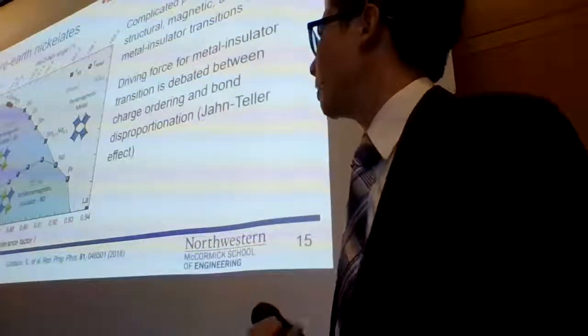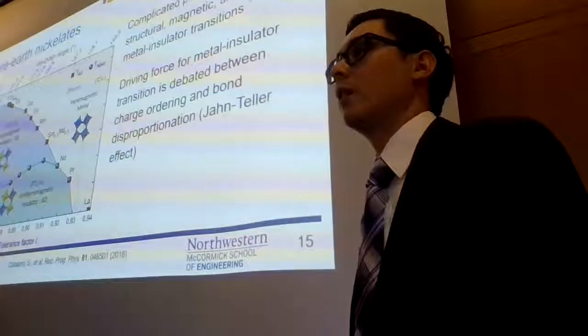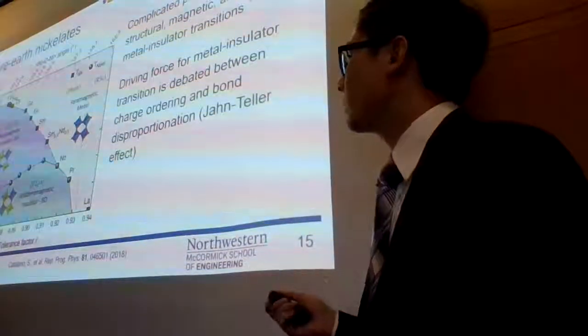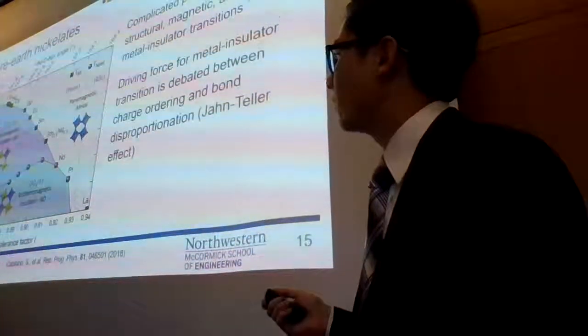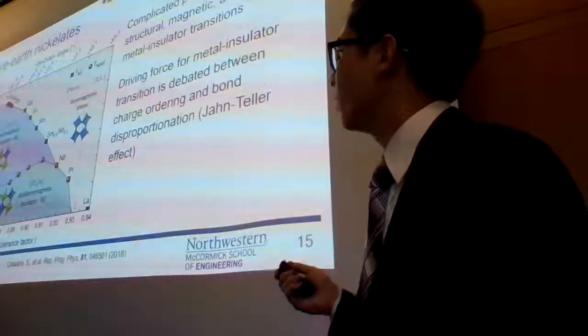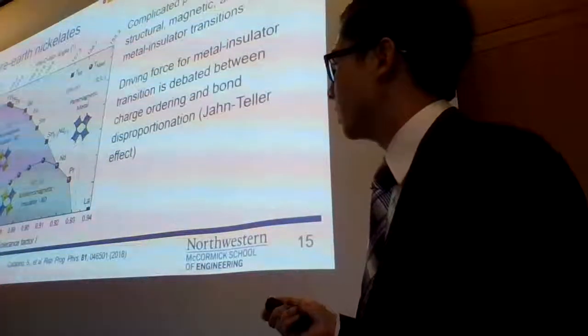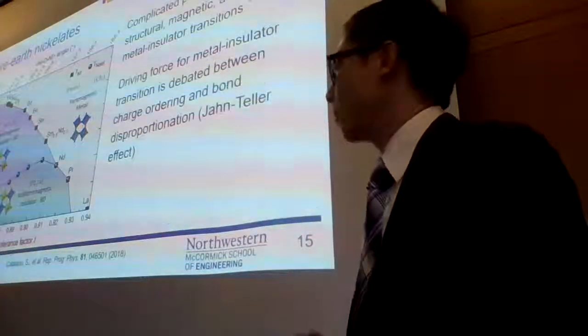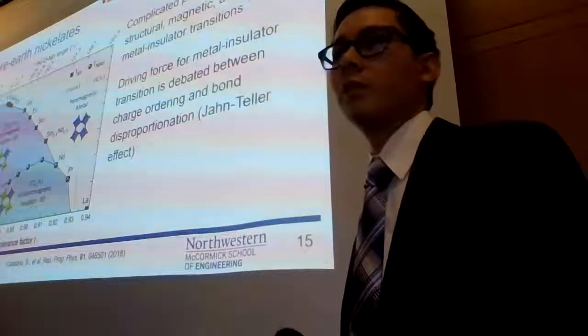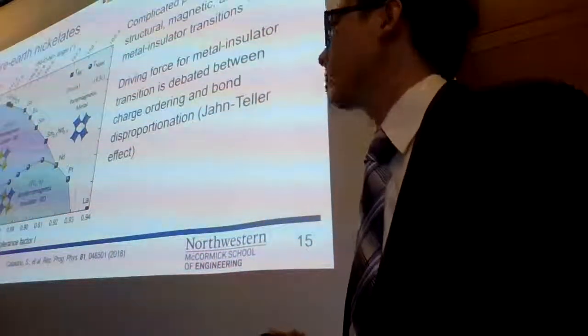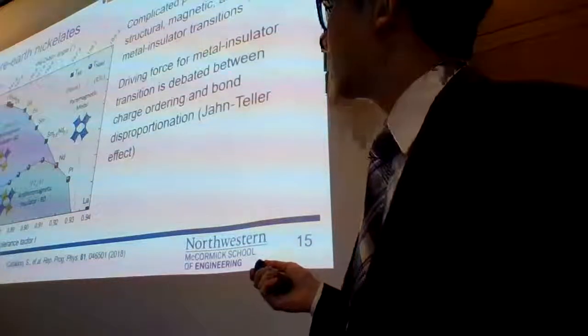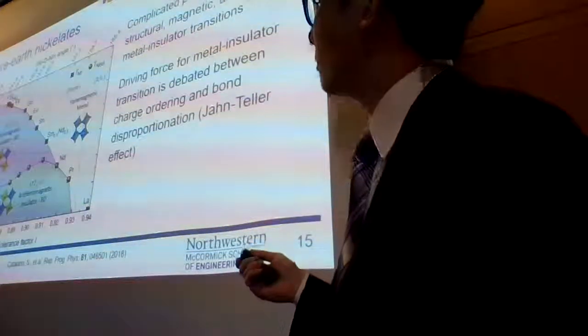So one materials family that does exhibit this transition is the rare earth nickelates. You have some rare earth cation, going from lutetium all the way to, say, neodymium or praseodymium, then nickel, then O3. These are perovskite analogs, like the structure I mentioned earlier, the corner-sharing ones, not the face-sharing ones. And they have this interesting phase diagram where they go from an orthorhombic